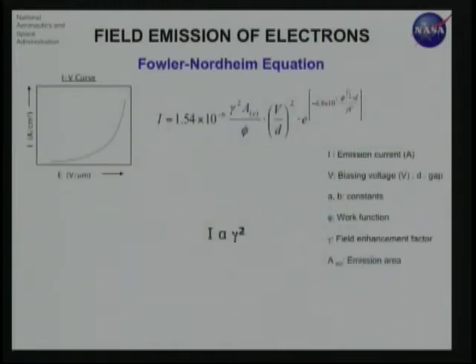Typically, these field emission equations follow the Fowler-Nordheim pattern. Here's the current, and that's gamma. Notice that the emission current varies as the square of gamma, the field enhancement factor, so it's a very important parameter. Phi is your work function, and here is your field, V over D, and current varies as the square of the applied field. So you can reduce the applied voltage by keeping the anode-cathode gap really small, and having very high gamma emitters that you can shape.